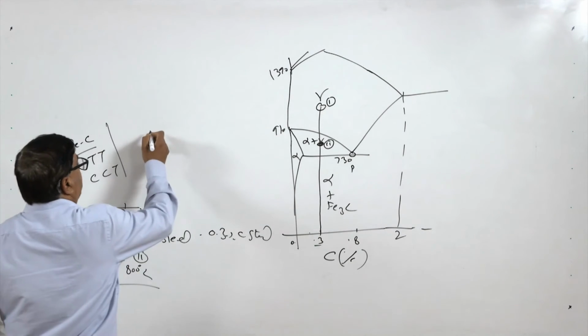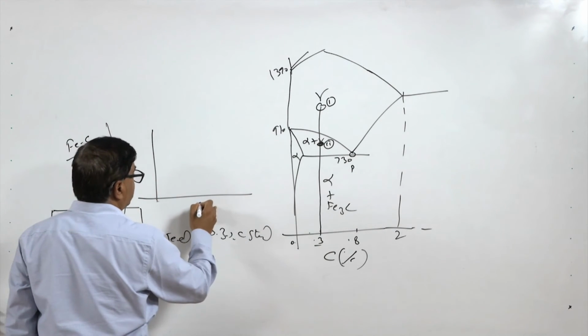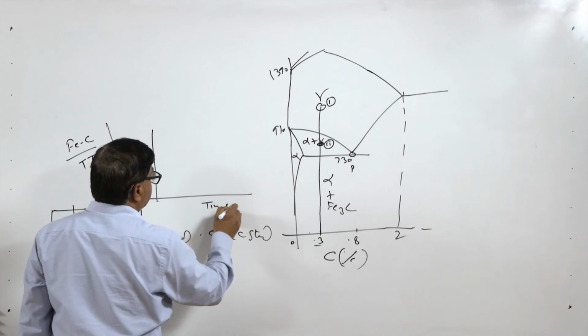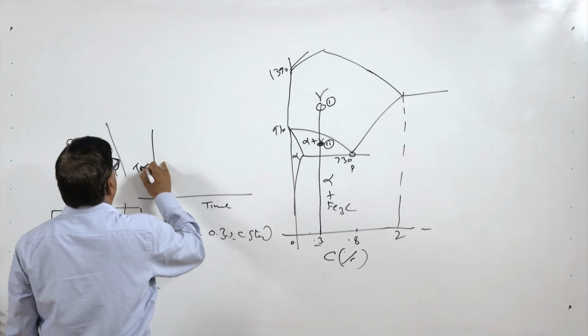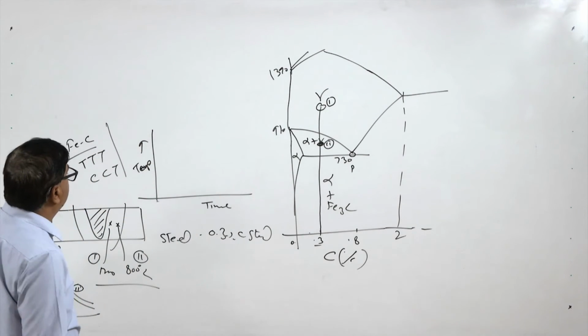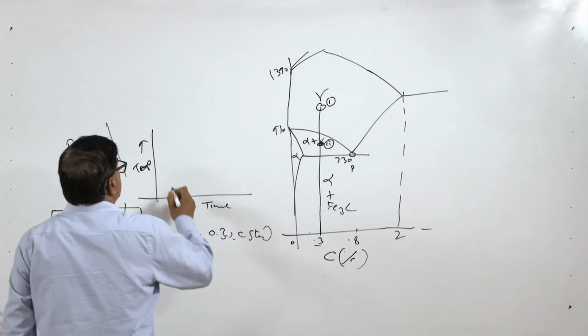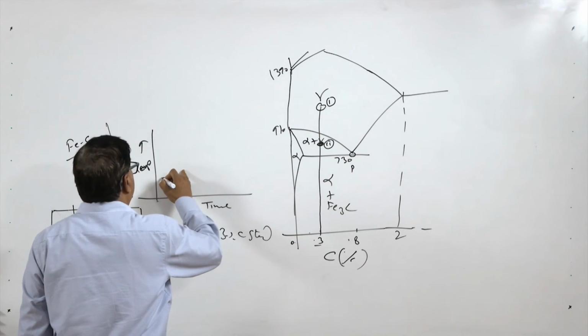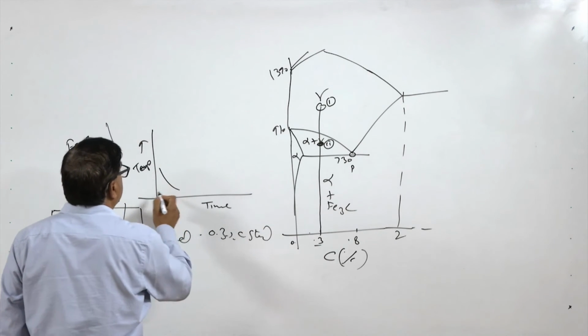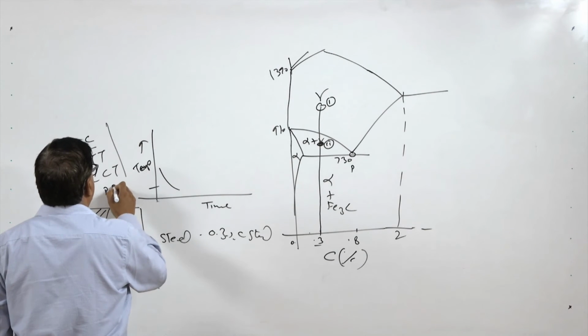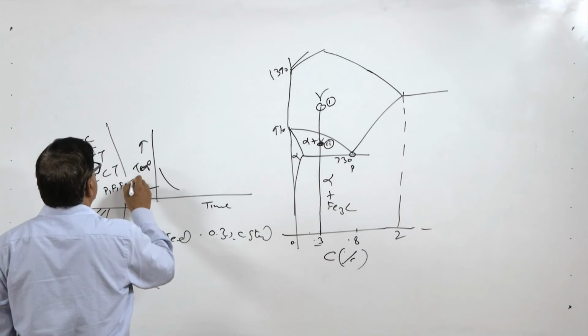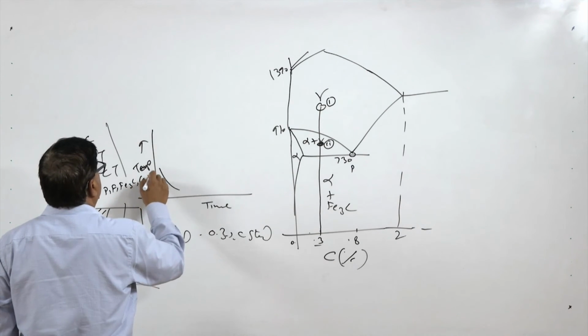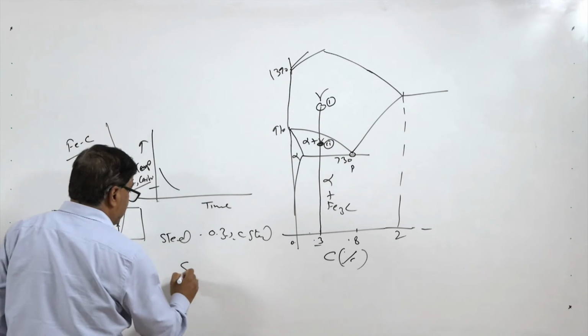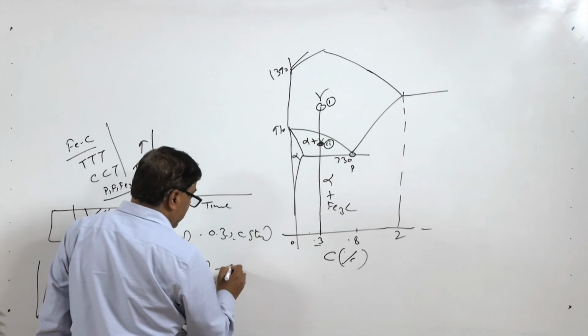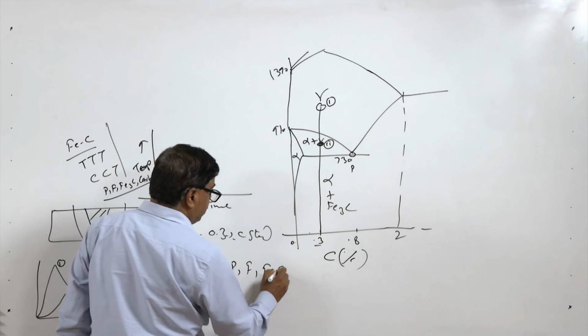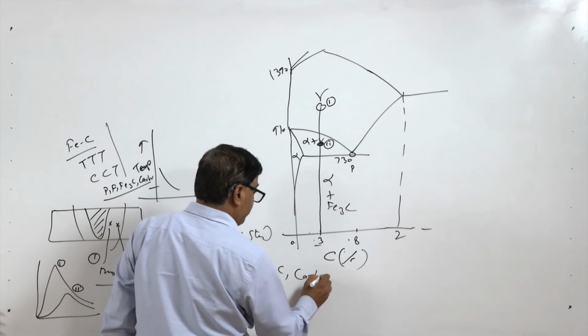So, how does it matter? For this we need to see this diagram, which shows how the time is affected as a function of temperature for homogenization. Here in the y axis we have temperature and in the x axis we have time. How does it happen? First of all our pearlite transforms into the austenite. Here we have pearlite, ferrite, Fe3C and then carbides if they are there in the steel. As per the composition, steel and alloy steel at room temperature will have pearlite, ferrite or cementite and then carbides if they are there.